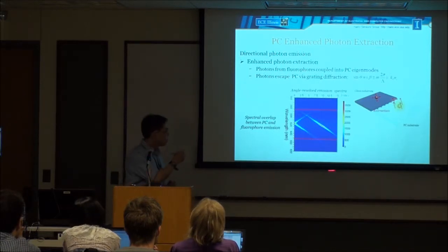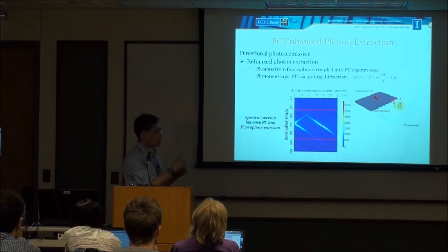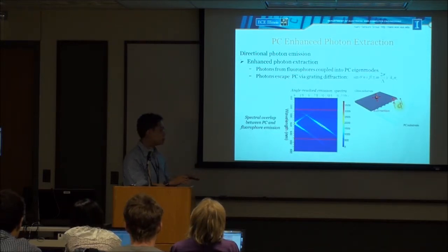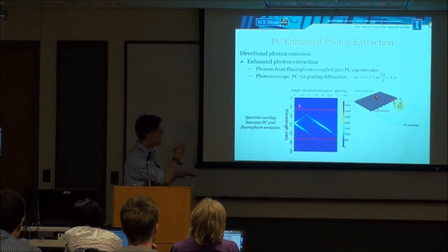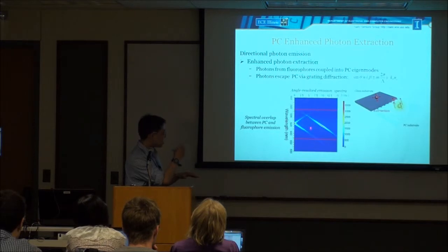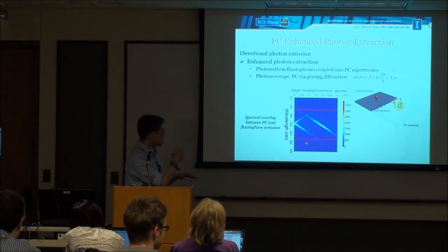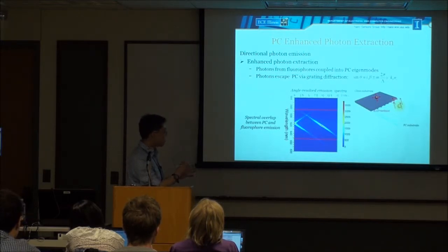As you see in this figure, we coat the dye molecule on top of the photonic crystal surface, and then measure the emission spectrum versus angle, which varies from 0 to 15 degrees. Most of the photons are confined between 0 and 10 degrees, depending on the mode. If you want to look at 620 nanometers, you can only look at a very limited number of angles.